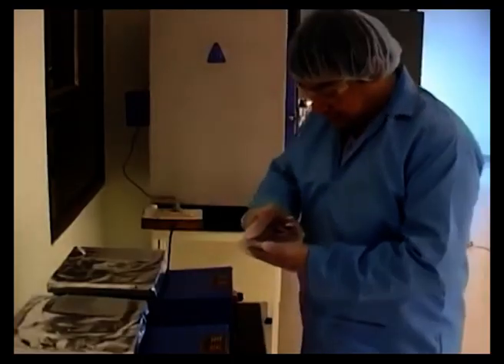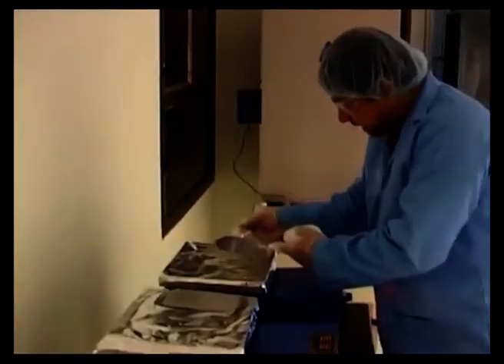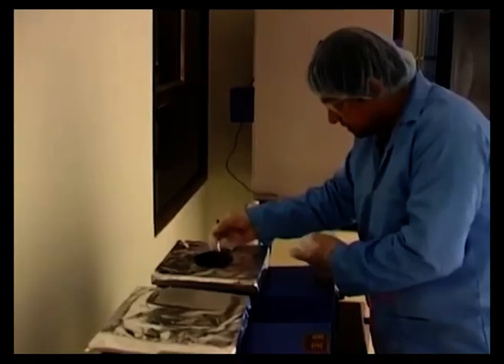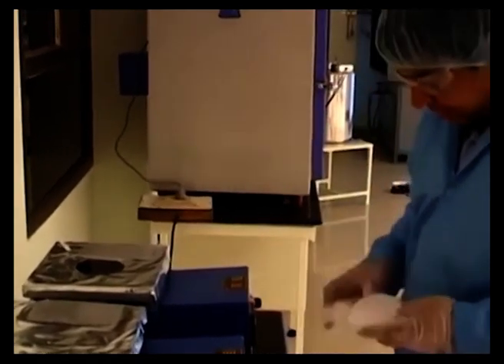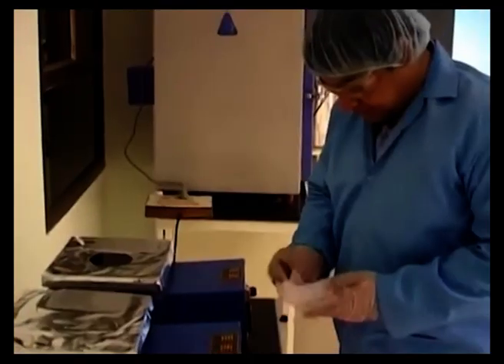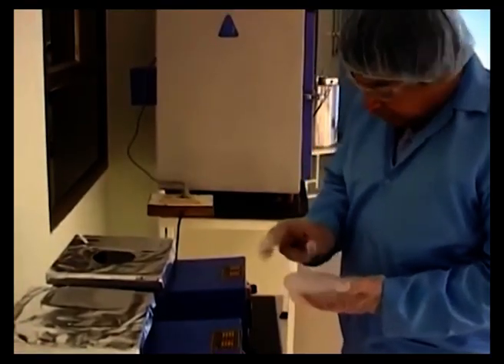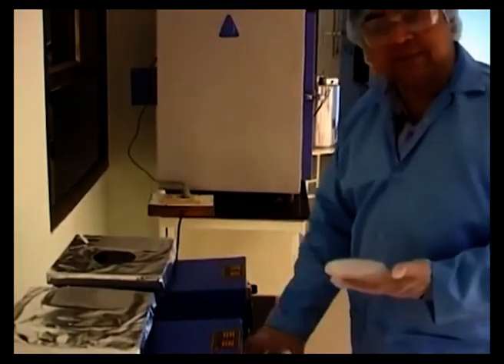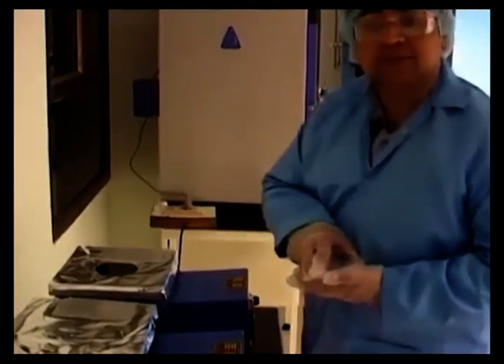So after picking it up from its location, we put it over this plate which has been set to a temperature of 95 degrees Celsius. We start on the stopwatch and set it to about 6 minutes time. So the idea is that, after 6 minutes, as we hear the second alarm, we should be able to pick this up and then again let it equilibrate back to the room temperature before the exposure process.